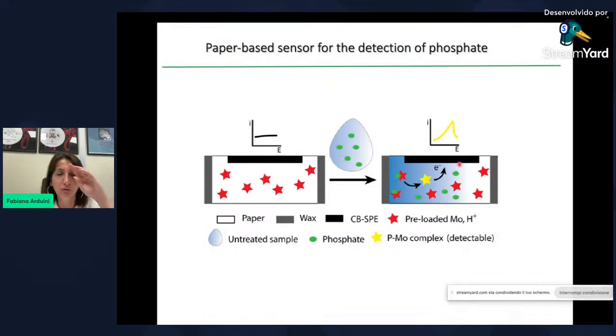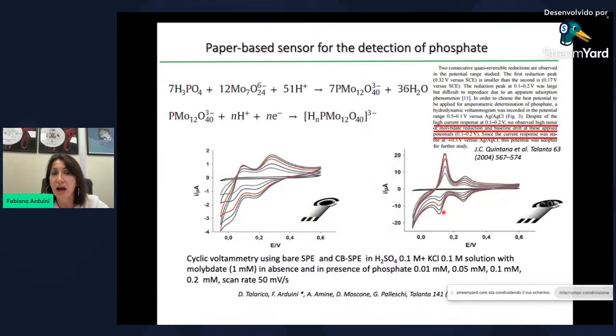For detection of phosphate, the reference method, usually in the lab for example, environmental monitoring, is based on the formation of the heptamolybdate complex with the phosphate, and after reduction with ascorbic acid to form a blue compound, so colorimetric detection. In this case, our idea is to replace colorimetric detection with electrochemical detection, removing the ascorbic acid, which is an unstable reagent, so it needs to be prepared every day. And so we need heptamolybdate, strong acid condition, that we preloaded in paper. And this is our starting point.